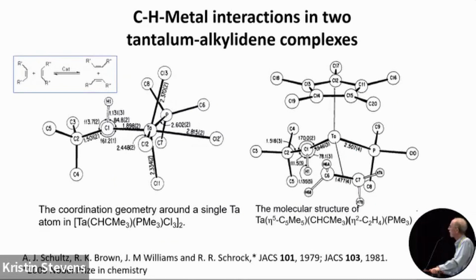Another type of CH metal interaction is observed in these 2 tantalum-alkylidene complexes. And these molecules were from Richard Schrock's laboratory at MIT. And these are tantalum complexes. This molecule is actually a dimer. We're only seeing half the molecule. But normally, if you consider that this is a carbene, then you would expect that all the angles around the carbon are 120 degrees, because it would have sp2 hybridization. That's not the case. So there's some interaction here, the hydrogen with the metal. And this angle here is now, I can't read it here, but it looks like 85 degrees. And this angle down here is 162 degrees. So it's very far from being 120. And the same is true in this molecule shown here.